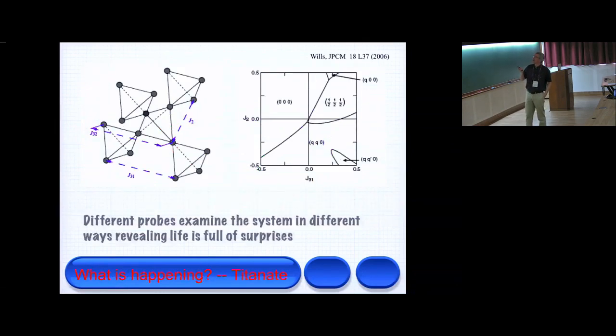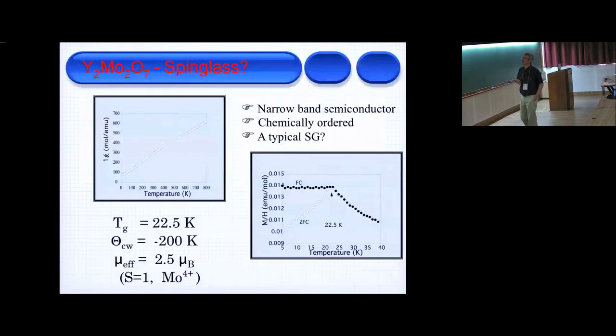A model that you can read in the literature shows this pathway here where there's a gap, so the next nearest neighbor can be J32 here through another magnetic ion or with no magnetic ion, and this is critical. So the gadolinium titanate, we believe, is in this part of the phase diagram, and the stannate is up here somewhere. And if we're smart enough, through other probes or equipment with pressure, for instance, we can start to move this around with maybe single crystals. So we're looking at that.